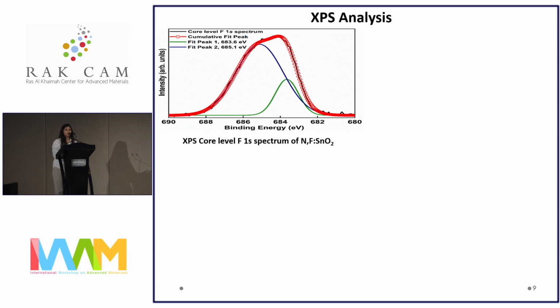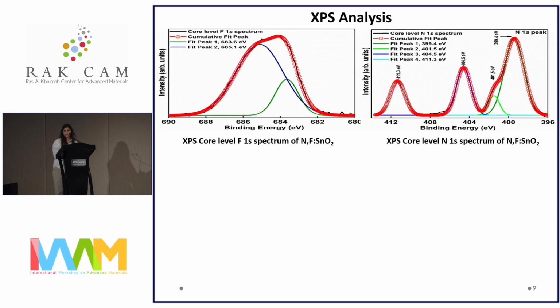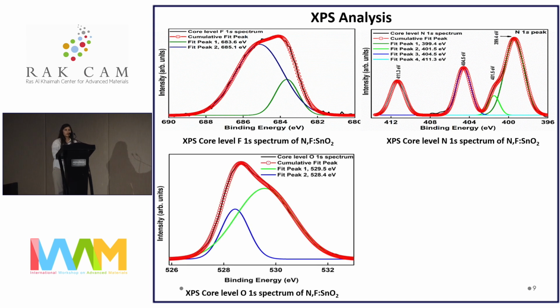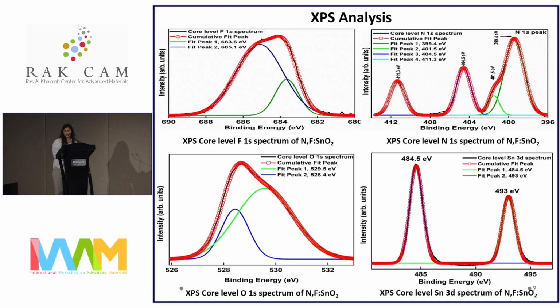XPS analysis was performed to know the elemental composition and oxidation states of the various elements present in the lattice. After deconvoluting the fluorine 1s spectrum, 2 broad peaks were observed using the Gaussian function, and these were representative of the different oxidation states of fluorine in the tin lattice. Similarly, the nitrogen spectrum was deconvoluted into 4 peaks, which states that nitrogen was present in 4 oxidation states in the lattice of tin oxide. Coming on to the oxygen 1s spectrum, we can see that there are 2 broad peaks in the oxygen 1s spectrum of nitrogen-fluorine co-doped SnO2. One of the peaks is associated with the lattice oxygen, while the other one is associated with the oxygen vacancies that have been created due to incorporation of nitrogen and fluorine in its lattice. Then the tin 3d spectrum represents that tin was present only in an oxidation state of +4 in this lattice.